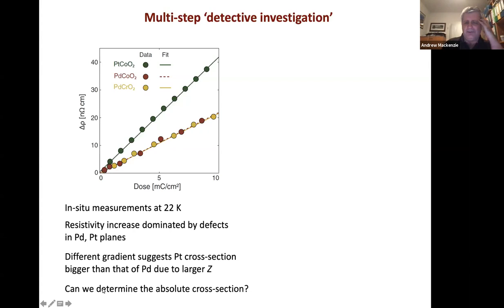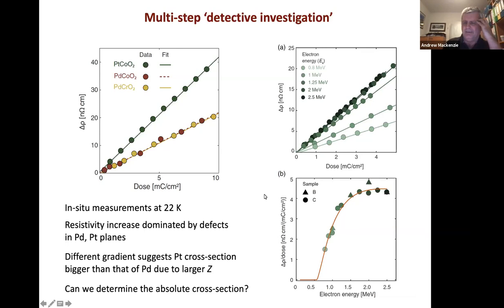So then, without talking to me about it, they started to think to themselves, does that mean we could obtain the absolute cross-section and turn this into a genuinely quantitative measurement? They aren't the very first to do this, but they did it themselves and didn't rely on software packages. They did all the relevant calculations themselves. The accelerator can be run at different accelerating voltages from about 800 kilovolts in practical terms to 2.5 megavolts. So they did a series of runs and showed that indeed on the same sample, the rate at which you gain resistivity is energy dependent. You plot out all of those rates and you see the energy dependence, and you do a fit through them based on scattering theory, but you can't use the Rutherford cross-section because it's an approximate one, which isn't good enough for this. You have to use the full relativistic Mott cross-section.